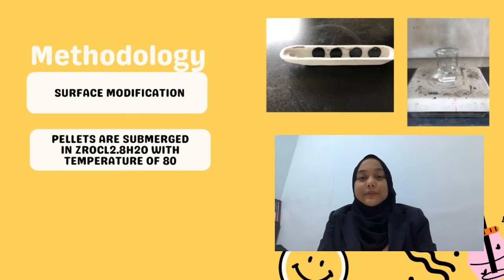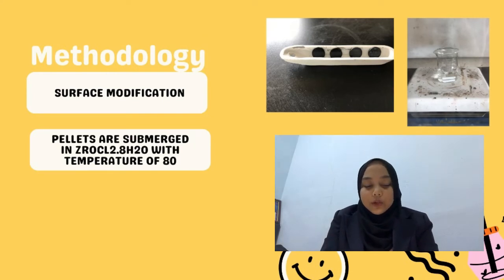The last step of the sample preparation is surface modification. There are 2 types of LSCF pellet made. One is pure LSCF while the other one is submerged in ZrOCl2 8H2O at a temperature of 80 degrees Celsius. The temperature is to ensure that the excess strontium is removed to modify the surface with metal cation. Approximately 0.46612 gram of ZrOCl2 8H2O was added to 100 ml of deionized water.